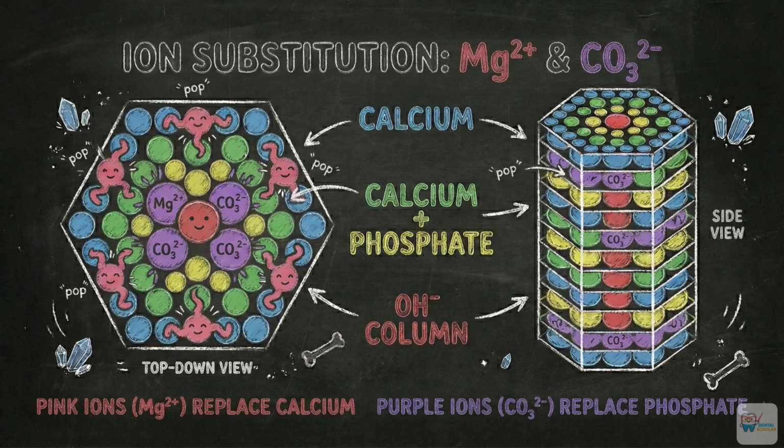So it is made up of several such crystal lattices, several such repeating units, right? So during the early stage, when this hydroxyapatite crystal is forming, magnesium and carbonate get incorporated. So they will be found more towards the core of this crystal. These ions distort the lattice and weaken the crystal, which is why deeper and immature enamel is more acid soluble.